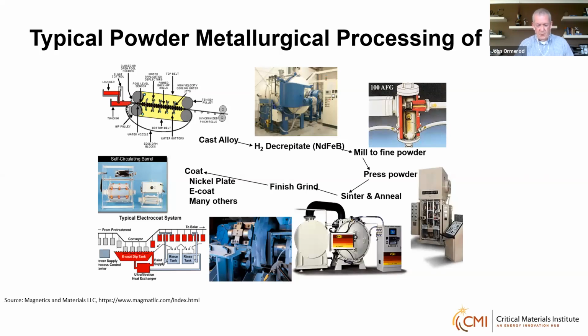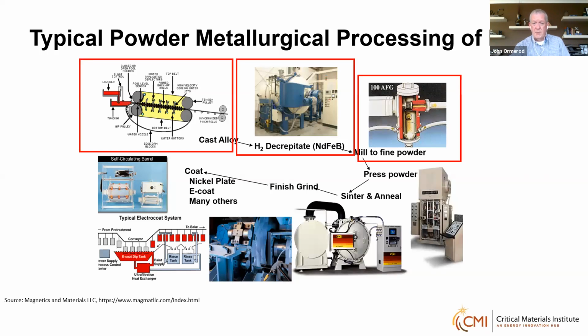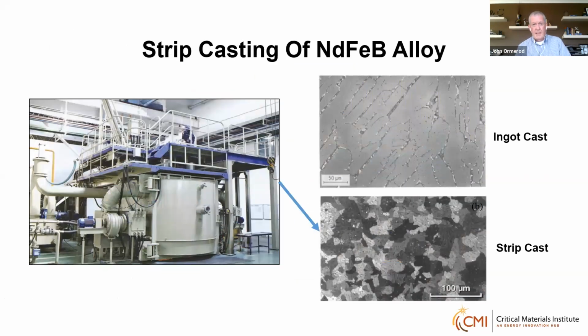Now, I just want to talk about three of these process steps, which are actually upstream processes that I personally believe have really contributed to the improvement in the magnetic performance we see in these materials, and to a certain extent their corrosion resistance. And it's strip casting, hydrogen decrepitation, and the fine powder milling process. Let me just go through those in a little bit more detail. Now, starting with strip casting. In sintered neodymium iron boron magnets, the microstructure of the starting alloy is critically important to the generation of the final magnetic properties of the sintered magnet.